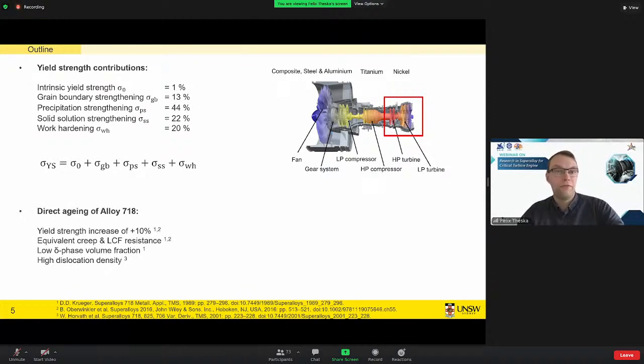To narrow it down a bit further, my work was mostly on direct aging of this alloy. And there have been some previous studies. This process is not completely new. So what's been shown is that the yield strength can be increased by 10% just through using this different process, while having equivalent creep and low cycle fatigue resistance. So there are no major trade-offs when using this process.